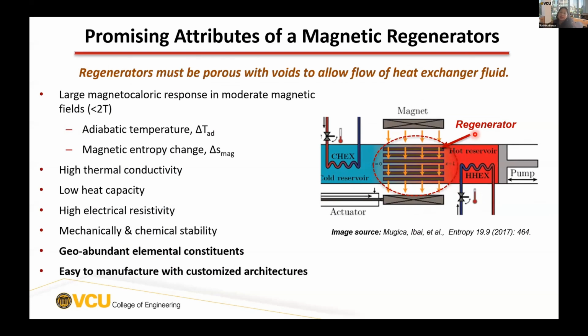In ideal circumstances, this regenerator is made entirely of a magnetocaloric material. It demonstrates a large magnetocaloric response, manifesting as an adiabatic temperature change (delta T) and a magnetic entropy change (delta S) at moderate magnetic fields, around less than 2 Tesla. The material should have high thermal conductivity, low heat capacity, and high electrical resistivity to reduce eddy current losses, because within the AMR device, the regenerator moves in and out of a magnetic field.